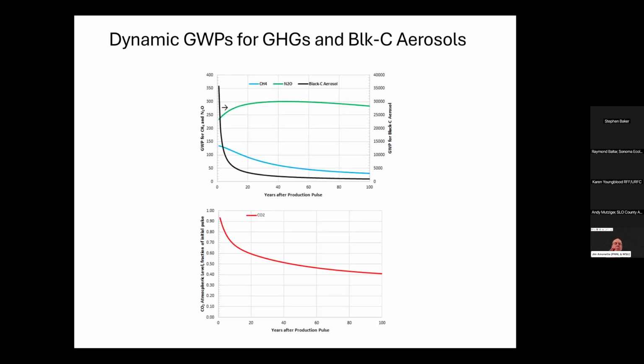I want to just point out quickly, it's a dynamic analysis, and so what we're trying to do is account for the dynamics of the concentrations of greenhouse gases and aerosols in the air after you have a pulse during the production. So at the top, I show the changes in global warming potentials for methane in blue, nitrous oxide in green. They're on the left axis. So you see methane starts around 130, and by the end of 100 years, it's down around 30 or so. Nitrous oxide starts around 180, comes up to about 300, and then slowly tapers off.